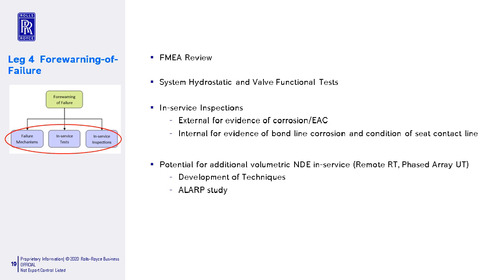As with the current manual globe valves in service, we carry out inspections looking for evidence of corrosion or EAC, and a number of the valves are removed and sectioned in order to assess the valve seats for evidence of bond line corrosion, and check the condition of the seats through life. This approach isn't going to change for the AM valves. Those in-service inspections will remain.